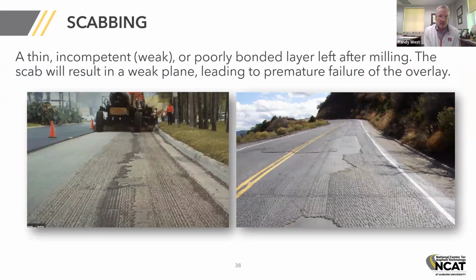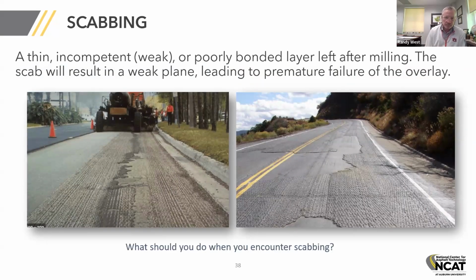So scabbing is leaving a thin, incompetent, or poorly bonded layer after milling. And that scab will result in a weak plane, not between what's tacked and what's on top of it, but between that scab and what's underneath it. And that's obviously going to lead to cracking or a debonding issue or poor performance. So my question to you is, what should you do when you encounter scabbing? Most people say nothing.